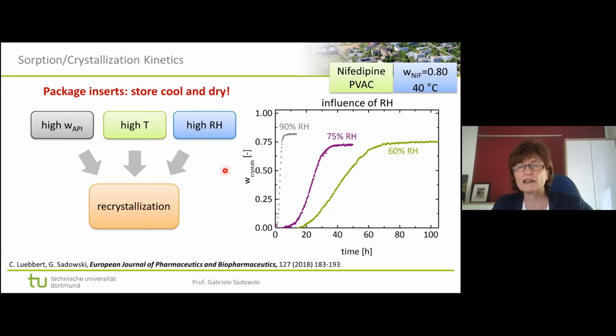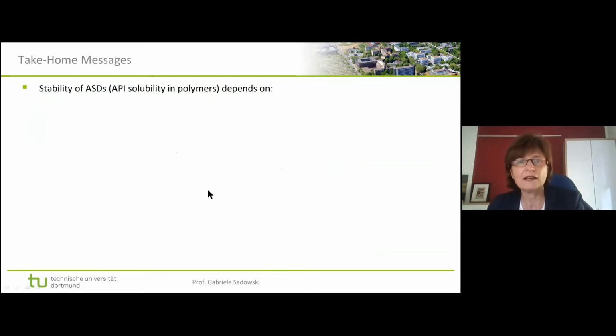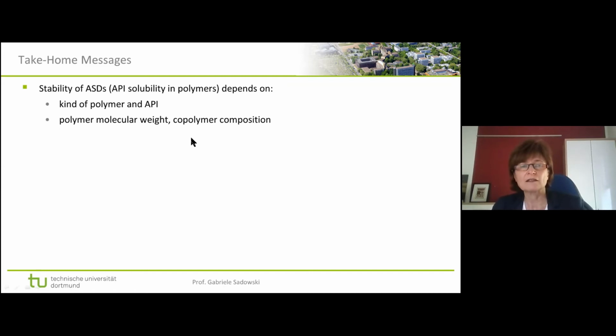So looking at this phase diagram, everything makes sense, and we are now also able to quantify this by using thermodynamics. And with this, I come to my take-home messages. Talking about stability of ASDs in thermodynamic terms, for API solubility in polymers we have to account for the kind of polymer and API. The API is usually fixed, but the kind of polymer can be changed at least to a certain extent. It also makes a difference with the molecular weight and copolymer composition. I did not show that here, but it does make a difference. Temperature is an important point, and most importantly, humidity is something you should really avoid.